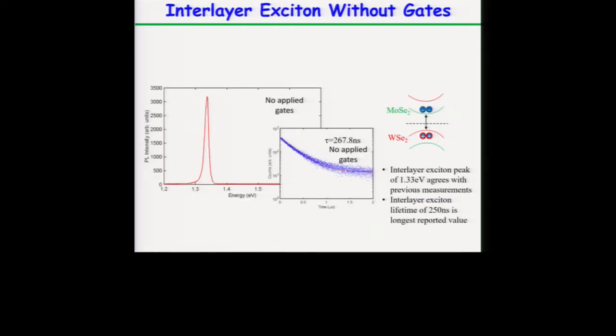Now we can measure the lifetime. We have gates that we haven't used yet, but we can measure how long it takes for the excitons to recombine at the same spot of the laser generation. We find for this sample it takes around 260 nanoseconds to recombine. As I mentioned before, in a single-layer two-dimensional TMDC, the lifetime of an exciton is around 2 picoseconds. So we have increased the lifetime by 5 orders of magnitude compared to a single layer.